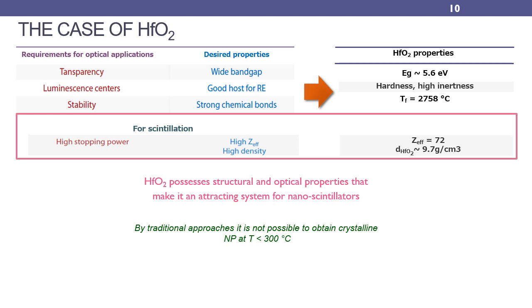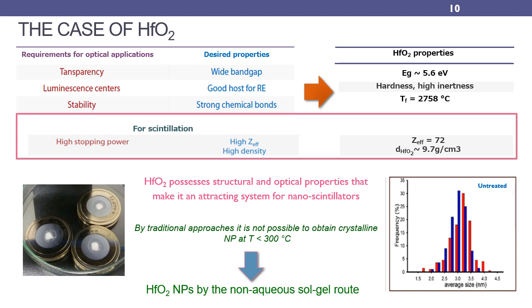One of the major drawbacks of hafnium oxide, that is the high melting point hindering the creation of bulks, can be surpassed by producing nanocrystals through the non-aqueous sol-gel route. Indeed, we obtain monoclinic crystals of hafnium oxide with a size of 3 nanometers in form of white powder.